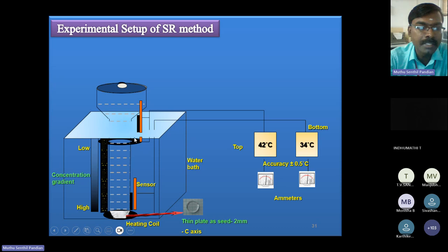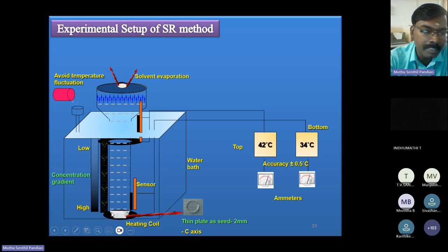And then we have to apply the temperature at the top and bottom portion. The top temperature is only for solvent evaporation, and the bottom temperature is only for growing the crystal. So the only idea is we have to maintain a uniform temperature between the seed crystal surface and the solution. The solution and the crystal surface temperature should be very uniform. Otherwise, there is a large possibility of the formation of multinucleation, microcracks, and milky opaque regions in the SR method grown crystal.